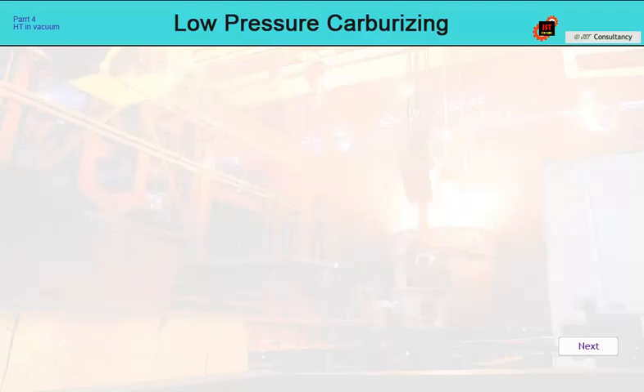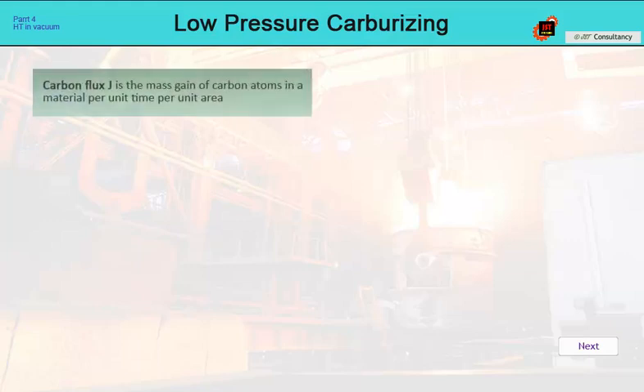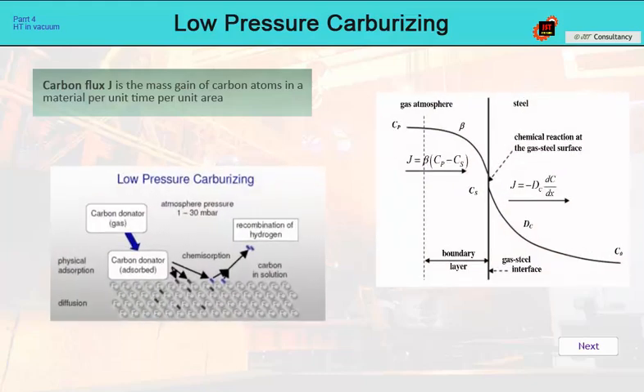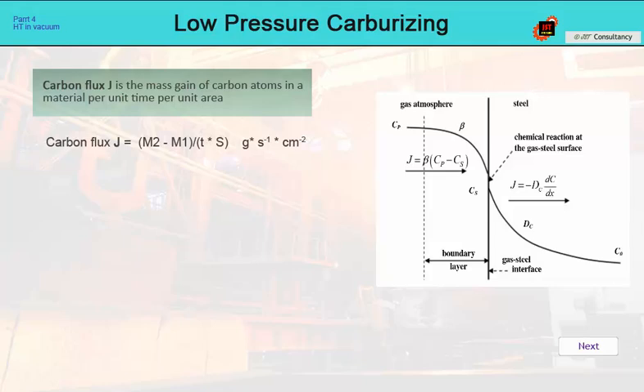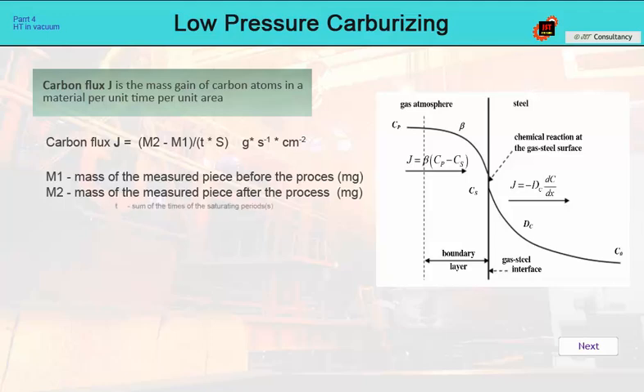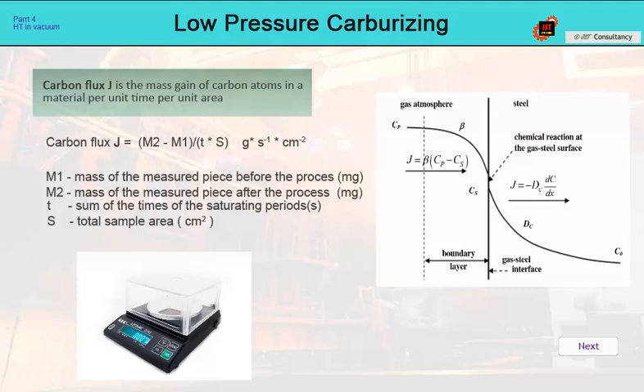In order to saturate the steel surface with carbon, we must ensure its sufficient flux. The carbon flux J is the mass increase of carbon atoms in the material and tells how many milligrams of carbon are introduced into a unit area of the batch per unit time. For example, in 1 hour of the process per 1 square centimeter of area. The formula for its calculation is as follows. In this formula, M1 is the mass of the measured sample before the process, M2 is the mass after the process, T is the sum of the times of the saturation periods, and S is the total area of the reference sample. To measure the carbon flux, we need ordinary scales with an accuracy of 1 to 100 milligrams and the ability to weigh up to 1 kilogram.